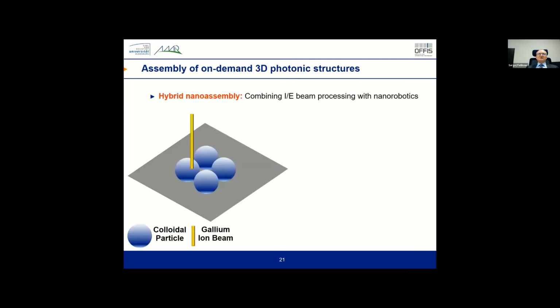So the newest development here in this collaboration is the technology which we developed for the first time: the combination of ion beam, electron beam, and nanorobotics for multi-layer nanophotonic structures. We apply EBID, electron beam induced deposition, just to make one layer of nanoparticles more stable. Then we apply focused ion beam etching to prepare the surface of the first level for positioning of the second level, and so on and so on.